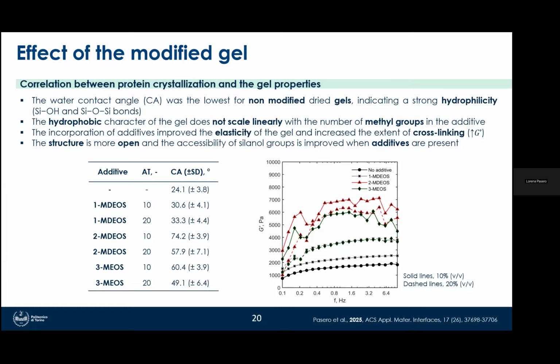And so when methylated additives instead are added to the system, the structure results in a more open one, where the accessibility of silanol groups is improved when the additives are present. However, the addition of 3 methyl groups results in a different structure where the storage modulus decreases. And this behavior was attributed to the excessive amount of methyl groups, which may have triggered the formation of local hydrophobic clusters and could have led to the reduced elasticity of the gel.